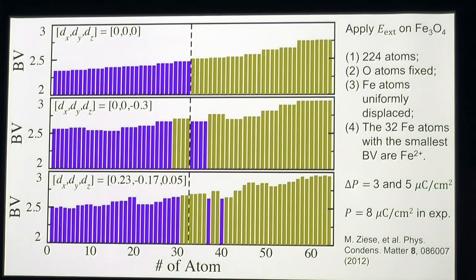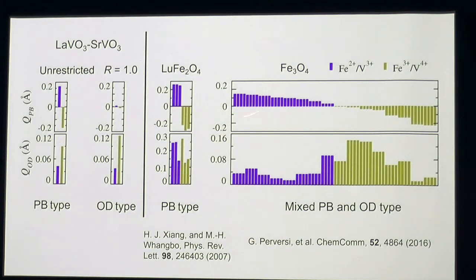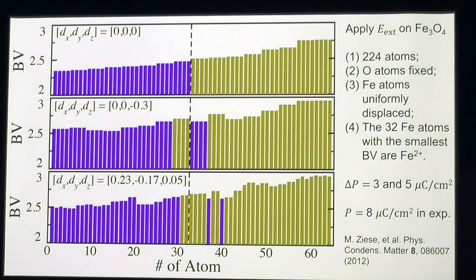Before the displacing and after displacing, we calculate the bond valencies of all the 64 atoms. And in each case, we assume that the 32 iron atoms with the smallest bond valence are iron 2 plus, and the other half are iron 3 plus. Here, I should also emphasize the sequence of the atoms are exactly the same as the sequence of the atoms in this graph. We can see that if we apply electric field compared with the original figure, the oxidation states of these atoms flip and induce a change in polarization. The change of the polarization induced by such a change in the charge ordering pattern is about 5 microcoulomb per centimeter square, which is in the same order of magnitude with the